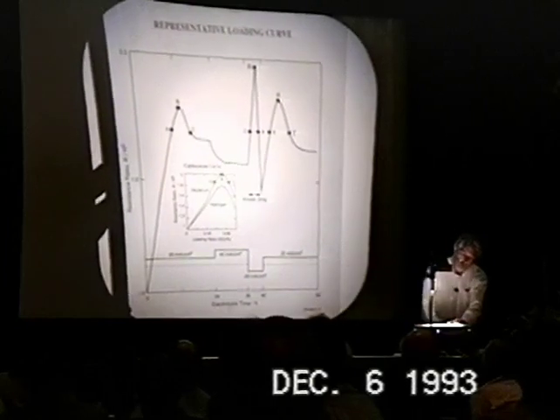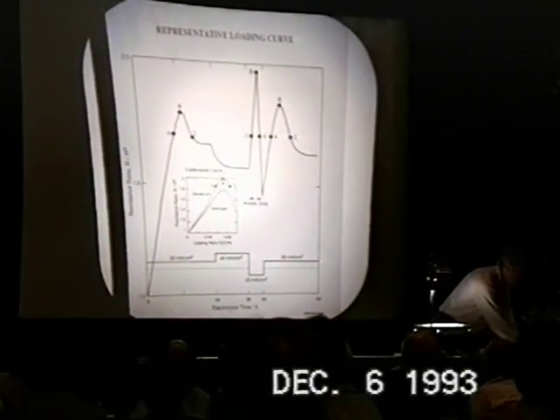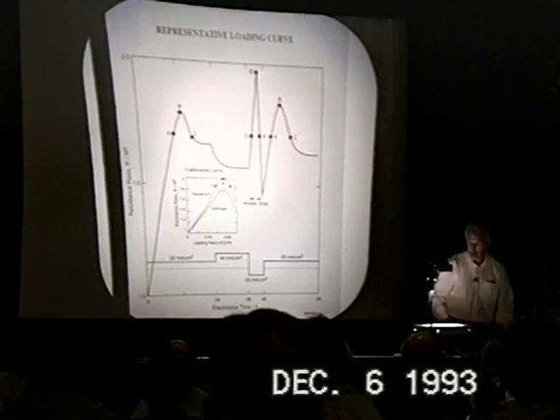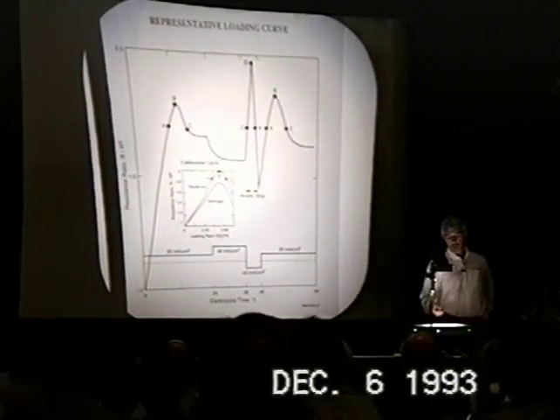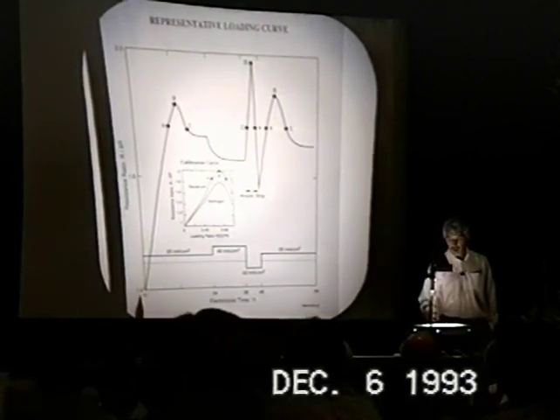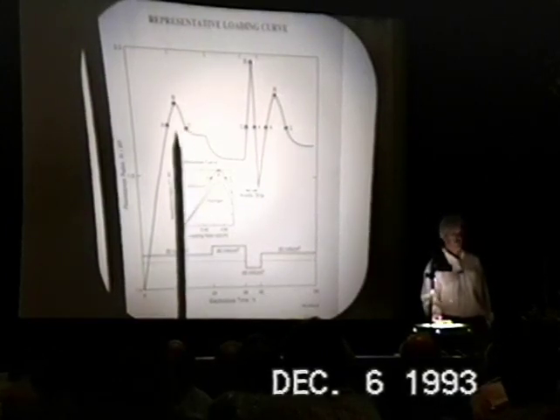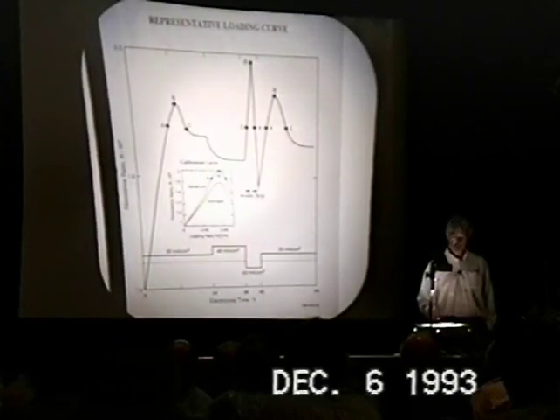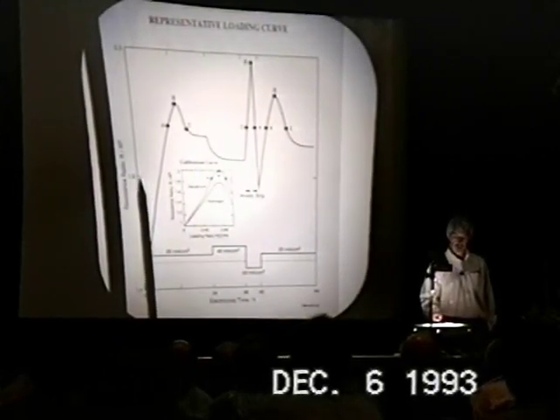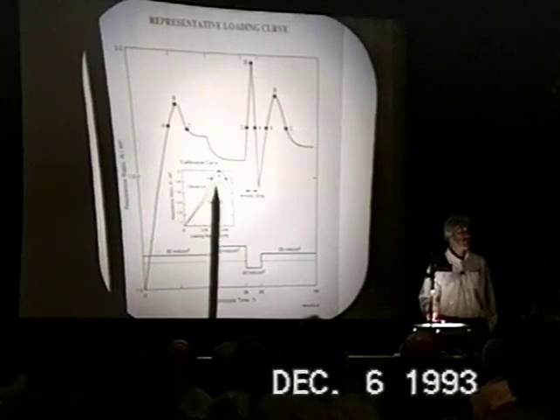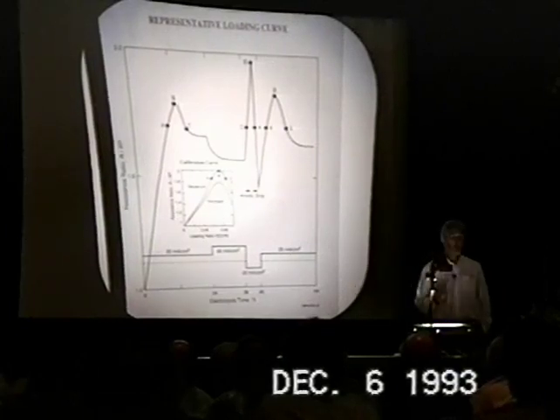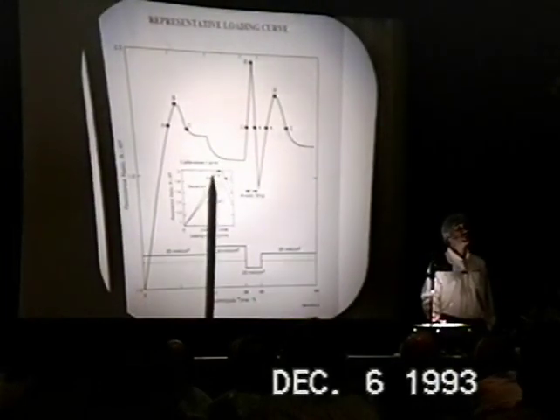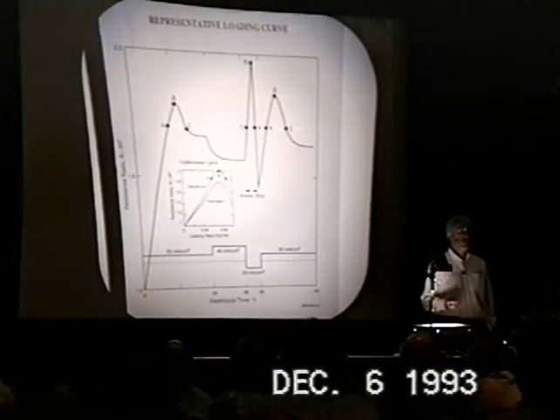I'm not going to discuss the results of that today. Here's a representative loading curve from which you'll be able to understand the results that I'm going to present. As I discussed before, resistance ratio goes up through a maximum, down the right-hand side, and hopefully down the right-hand side as far as possible. For reference, if we can get down to about 1.5 on the right-hand side of the maximum, that is a resistance ratio which is associated with a loading of approximately 1.0.